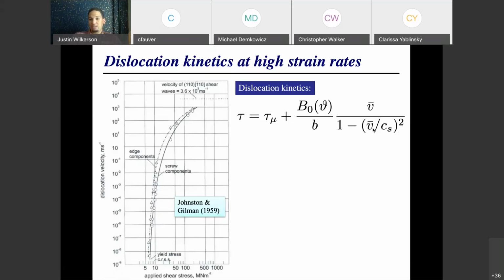That basically causes the right-hand term to blow up as the velocity approaches the shear wave speed. So to drive a dislocation at speeds that are close to the shear wave speed, it requires an infinite amount of shear stress. So that's that upper limit.